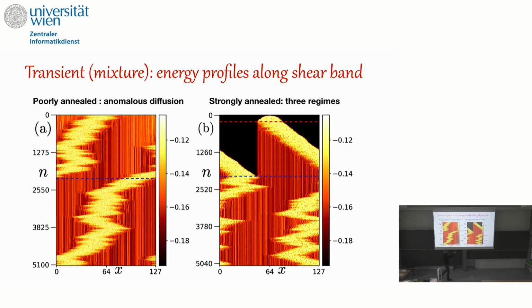Now, in the other case, when you have the very well annealed sample, this is much more interesting, because at the beginning you have to break the solid. So at the beginning you have the formation of the shear band that grows, okay? And now it doesn't move diffusively, it moves ballistically. It actually invades the black region, which is the very well annealed case, leaving the marginal solid, which is at the energy star. And only when it is able to reach all the sample does it start to diffuse, okay? And this is depicted in a movie.